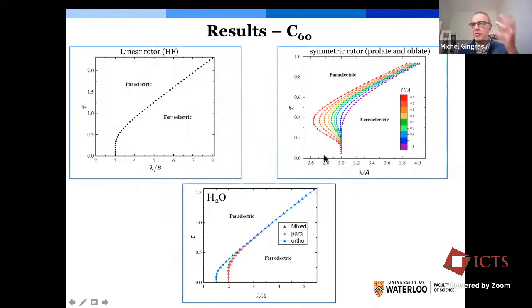And that has to do with the fact that the excited rotational energy levels carry more dipolar character than the lowest one. As those states become thermally populated, as one increases the temperature from the quantum disordered phase, one would actually enter into a ferroelectric phase and eventually, upon further increasing the temperature, return to the paraelectric phase. This kind of phenomenon has nowhere near been explored in encapsulated dipolar molecules thus far.